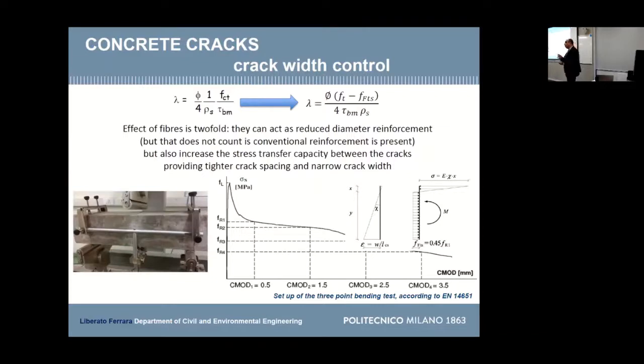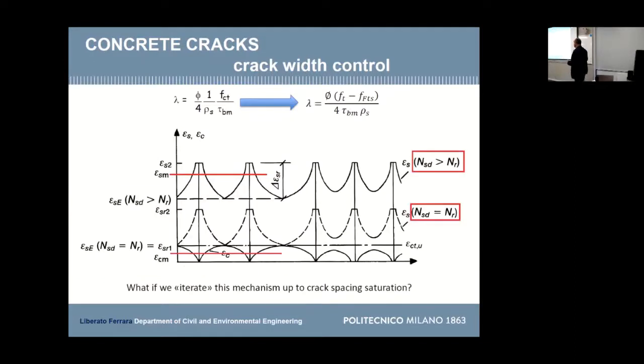So the code is made in such a way that fiber reinforced concrete is homogenized, is made compliant with ordinary reinforced concrete, because one of the issues could be that you can use both of them, fibers and conventional reinforcement. So you need a method to match them together and make a consistent design.